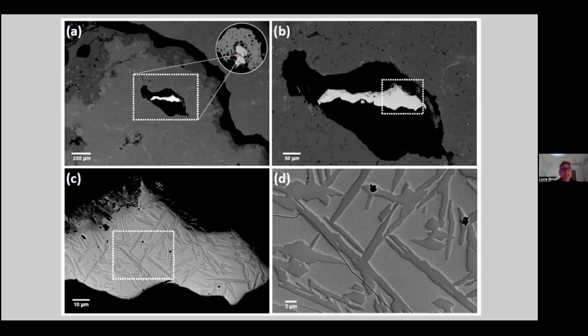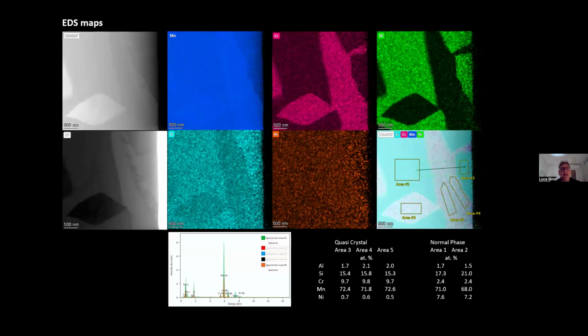And look at what I mean. This is a small grain inside the aluminum. This is the aluminum. It is brighter because, of course, it contains manganese and nickel and chromium. And look at the blow up on the right, and again a blow up here, and again here. Look, it is a combination of acicular grains in a matrix of another kind. Well, we were able to collect a FIB lamella on this portion, and look at the chemical maps, which is pretty impressive because the acicular grains turned out to be enriched in chromium and the matrix in nickel. But when we carried out the diffraction of the acicular grains, it was impressive because it turned out